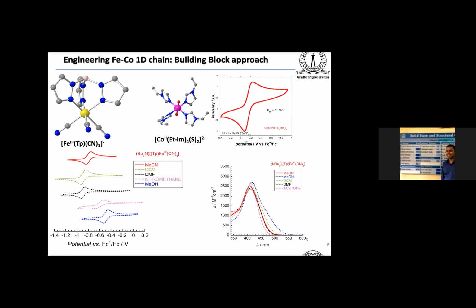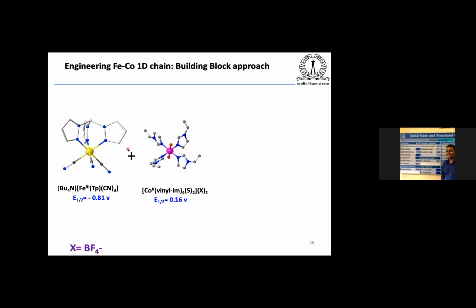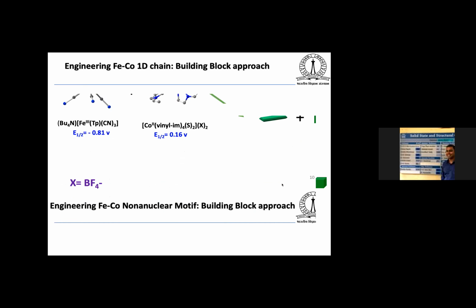Then what we did, we take these two building blocks and we react them together. We got very nice red color crystals when you use one particular technique. And also when you change the stoichiometry and solvent, we also got green color crystals. But when you saw in the microscope, we observed that there are two different types of crystal. One is block, another one is a plate-like crystal. We separate them mechanically, and we have studied the structure and physical property of the system.